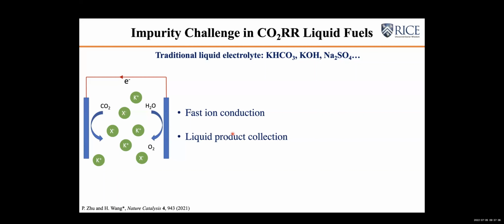But the second function of the liquid electrolyte for CO2 reduction to liquid fuels is product collection. So in this case, for formic acid, once the CO2 gets reduced to form formate, it will be continuously flushed out by the liquid electrolyte. So in fact, you are not producing the product formic acid. You are actually producing formate ions that are in a mixture with liquid electrolyte. So you will always have to do a downstream product separation process to extract the high purity and high concentration formic acid product to really compete with the traditional chemical engineering approach.